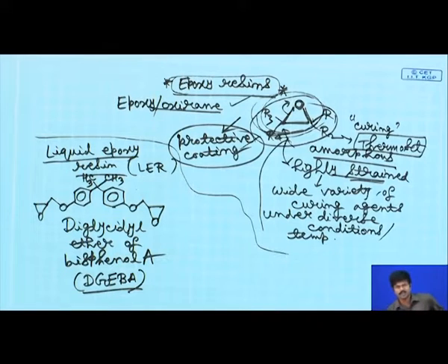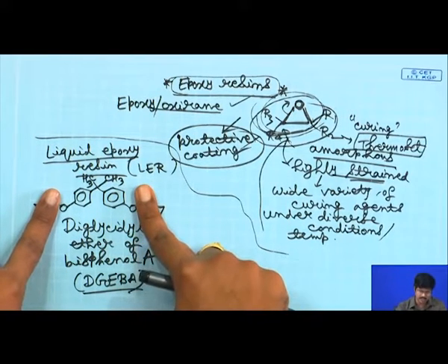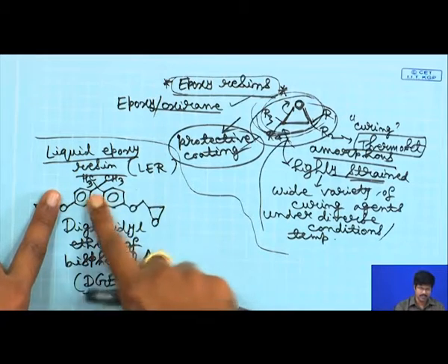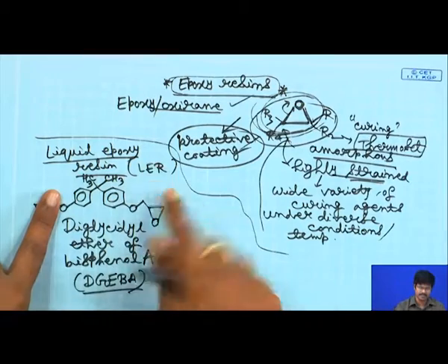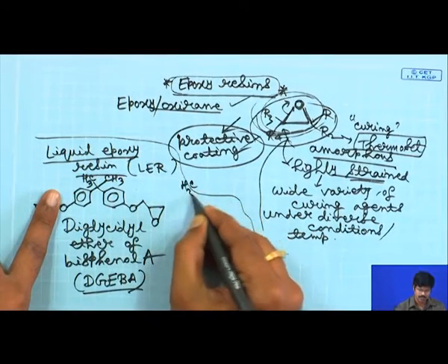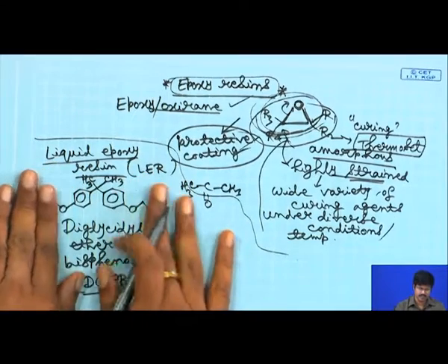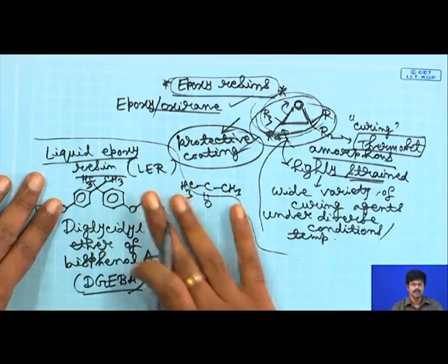We will explain why. Now, a little bit more about the name. So, if you have an alcohol on both sides, this is your bisphenol A. We already talked about bisphenol A. So, basically you start with phenol, which is your phenyl ring, and then OH. You react your phenol with acetone, then a condensation reaction occurs and you get your bisphenol A, OH on both sides.